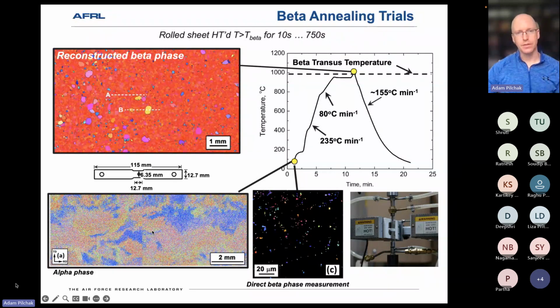But what I think is the most interesting is if you zoom in really far, do very high spatial resolution mapping to the point where you can directly measure the beta phase, we see a whole range of different orientations. So I've got some reds, blues, pinks, greens, yellows, so a variety of underlying BCC orientations. However, and I'll say one other thing.